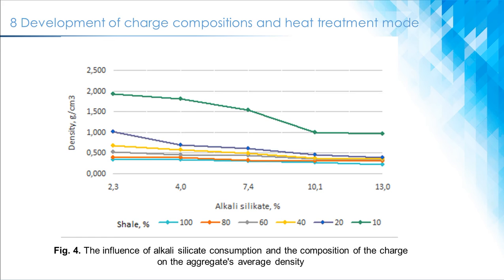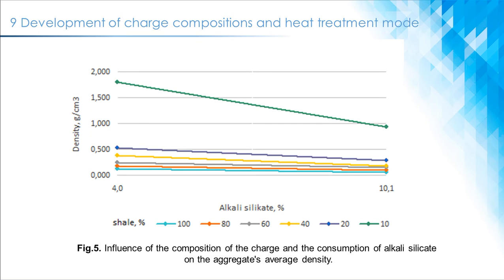Previous studies have shown that using a mixture containing unmilled sludge and shale results in low-strength granules with low porosity and high average density. Therefore, all further studies were carried out only on mixtures with ground components. The results are shown in figures 4 and 5. Dependencies show that the most intensive decrease in average density occurs when there is up to 40% shale in the charge. A further increase in the shale amount reduces the average density slightly, but the granule strength sharply decreases, and the pores increase due to increased gas release.